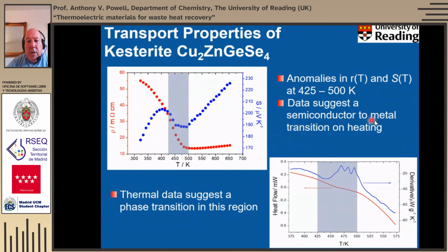Now, as I say, this has been described as a semiconductor to metal transition. I think it's unlikely to be a true metal because this is quite a high Seebeck coefficient of about 230 microvolts per Kelvin. And it's also quite a high resistivity of about maybe 15 milliohm centimeters to be a conventional metal. So our belief is that it's actually a transition from an activated semiconductor to a degenerate semiconductor.